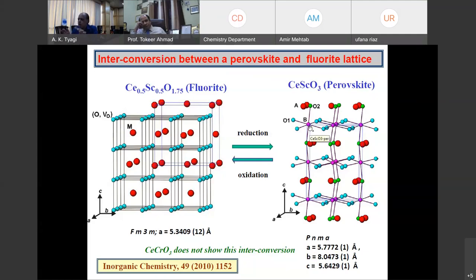So for making compounds which are interconvertible, you must very carefully select the right combination of cations which can satisfy the coordination number requirements of the two end member structures. In the case of chromium, chromium 3+ is very comfortable with octahedra, but chromium 3+ never adopts cubic coordination. That's why CeCrO3 showed a phase separation, whereas CeScO3 showed a phase transformation from perovskite to fluorite.